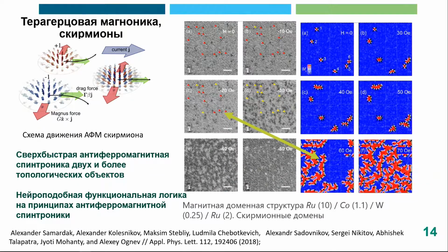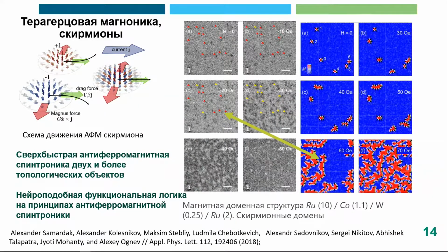The more popular material, which you can find in real life, is antiferromagnets with a small ferromagnetic moment. In this case, the magnetic moments of opposite sublattices are not strictly parallel to each other, and they have some angle between them. Therefore, this material has some magnetic moment. However, it consists of two, or in some cases more, magnetic sublattices. The value of magnetization depends on the exchange interaction between sublattices. If you consider the energy of this exchange interaction and divide it by the Planck constant, you will get immediately the frequency related to this excitation, in the terahertz scale.